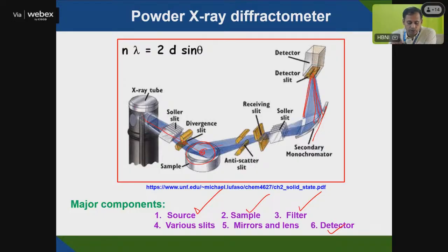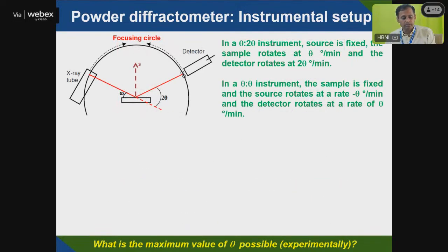So you will see each of these components individually, but mostly for the source we take a copper source. The tungsten filament, by thermionic emission, gives electrons which interact with the anode, that is the copper anode, and remove electrons, so copper K alpha will come out and fall on the sample surface. Then it will pass through different stages and go to the detector. The detector and the source are the important components of X-ray diffraction. So we will see those individually also.